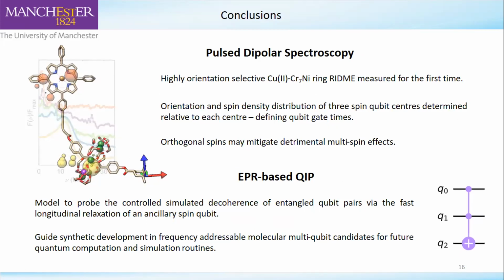So to conclude, there's sort of two parts. On the pulse dipolar spectroscopy side, we were able to do these highly orientation selective copper chromium-7 nickel ring interactions, and be able to measure those for the first time. We were able to look at both the orientation and the spin density distribution of 3 spin centers relative to each other, and